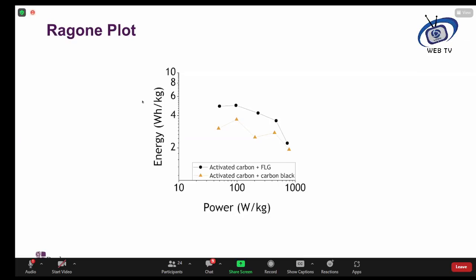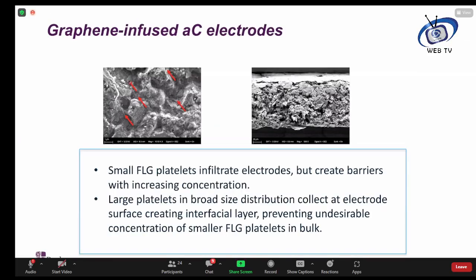We believe that this is because, as we say, we infuse the graphene into the body of the electrode, and you can see where these arrows point, where we've taken a cross section through one of the electrodes, that there are graphene platelets, and these provide links between the activated carbon particles and therefore improve the conductivity of the electrode. But unlike carbon black, which does the same thing, the graphene platelets are electrochemically active. They also participate in creating the capacitance of the electrodes.